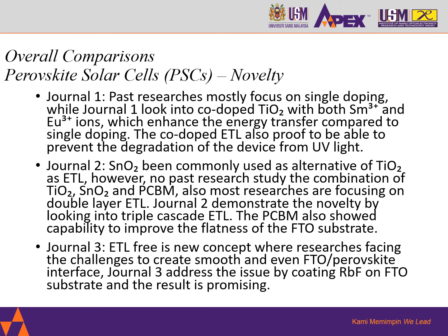Talking about the novelty of each journal, the first journal is looking into co-doped TiO2, whereas past research only focused on single doping. The result from this journal shows that the energy transfer is improved compared to TiO2 with single doping. The co-doped ETL is also proven able to prevent the degradation of the device from UV light.